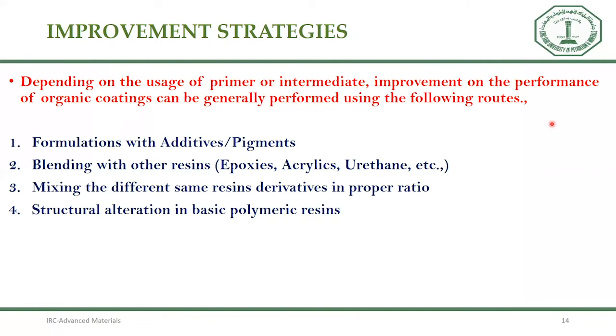So how do we improve the performance of the epoxy coatings? There are 4 different strategies. One, formulation with additives and pigments. We can add some innovative pigments, or some additives, to improve the resultant properties of the epoxy coatings. Then we can blend with similar kinds of resins, like taking epoxy and adding some acrylics and urethane. It is a kind of blending to make hybrid resins. And we can also mix different derivatives of the same resins in proper ratio, as well as alter the structure of the basic resins.